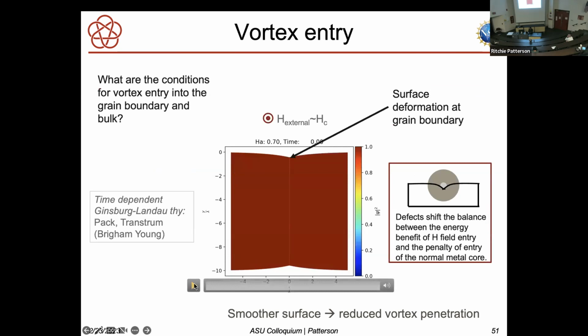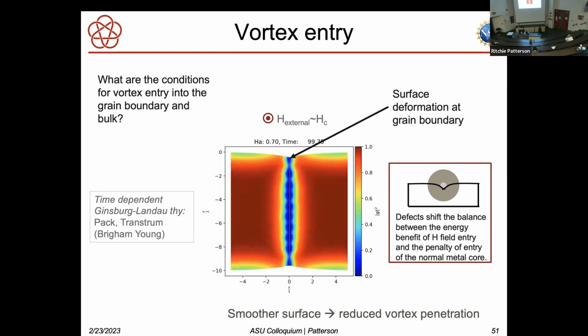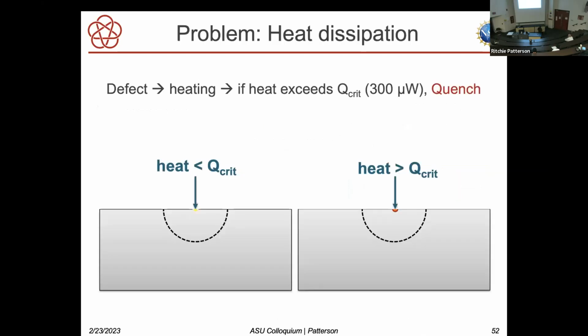So this is niobium-3 tin at one of those grain boundaries, and you're going to see vortices enter. There's an external magnetic field here. So there are vortices coming into the material, and then bang, they go out into the bulk. And now those things are free to oscillate and cause heating. So this is a big problem. It turns out we need a smooth surface in order to prevent this from happening.